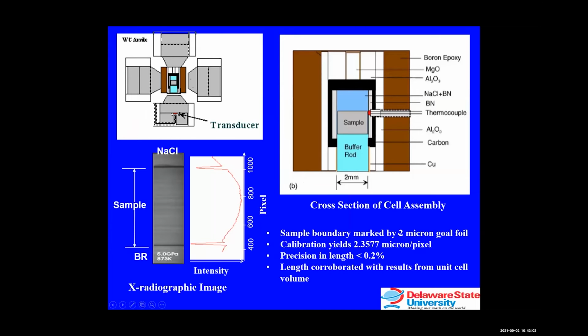So the top right is a schematic diagram of 4 of the 6 anvils of the DIA with a dual mode piezoelectric transducer mounted at the back for the lower anvil. The cell assembly on the right is made of boron epoxy, and the resistive furnace heater is graphite. A double-side polished alumina rod transmits the acoustic signal into the sample, which is inside a boron nitride sleeve and supported at the far end by a sodium chloride and boron nitride mixture.